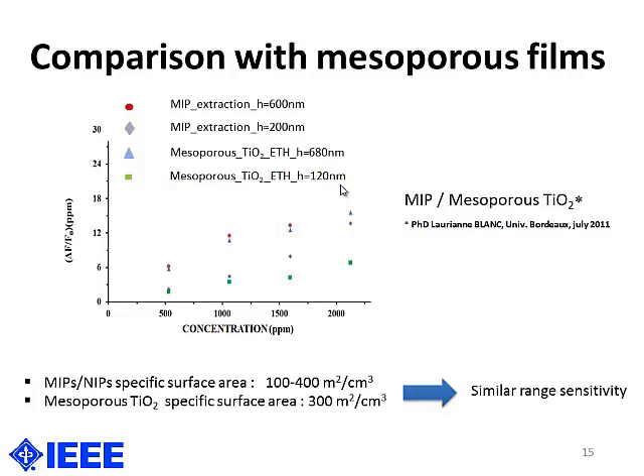This one just illustrates a comparison with mesoporous films of titania. They have been studied before for their applications in the lab. And in fact, we have similar specific surface areas for both MIP and mesoporous films, and also similar thicknesses, and we find a similar range of sensitivity for the detection of vapors.